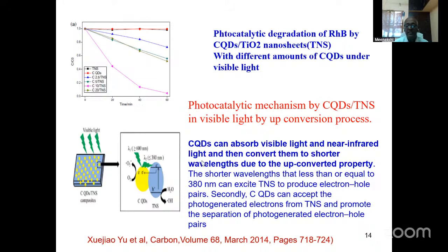And the specialty of this one is, you can see the mechanism here, that we are giving 600 nanometer radiation for exciting the carbon quantum dots. So the carbon quantum dot is the photocatalyst, and you are giving 600 nanometers, but once you give 600 nanometers, from the carbon quantum dot you are getting 360 nanometer light. So this is called upconversion fluorescence. The 360 nanometer light is efficient. It is also capable of exciting an electron from the TiO2. That is, TiO2 requires only 360 or 370 nanometers for excitation. Band gap energy is equal to 360 nanometers.